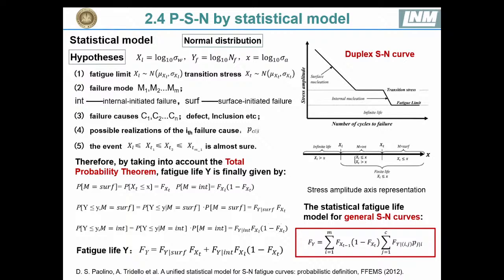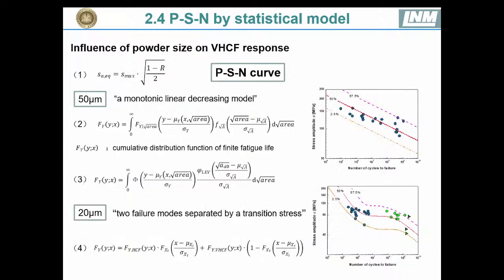And in addition, a statistical model developed by our collaborators, Andre and also David, is also used to perform a statistical analysis of the SN curve. It assumes that the fatigue life follows a log-normal distribution, and from surface to subsurface crack initiation there will be a transition, and there will be two curves, and these two curves can be modeled by assuming that the mean value of the fatigue life follows a log-normal distribution and is also a function of defects in the specimen. The defects of the specimen are assumed to follow a Gumbel distribution, and once we get the distribution of the defects, the fatigue analysis can be done.